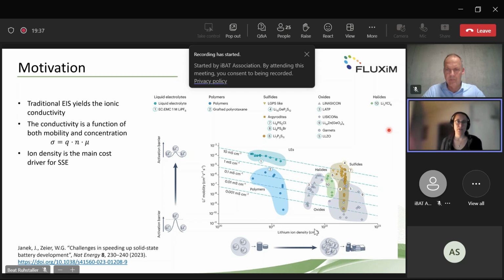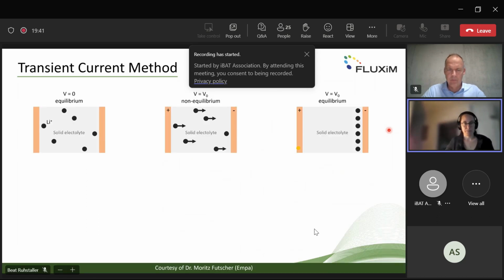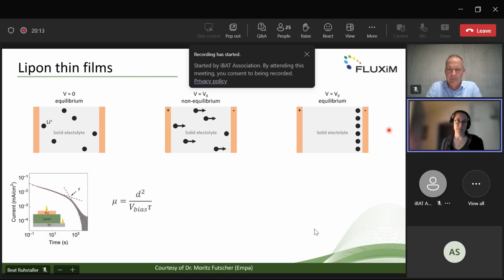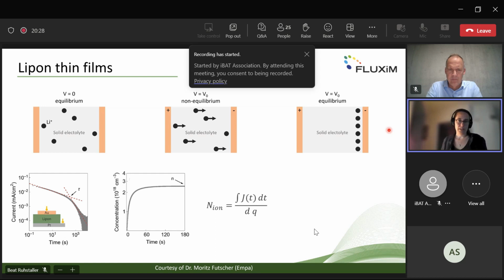in the production. So to introduce this method, it's actually pretty simple. Here is a sketch from Moritz Futscher from EMPA. You have basically a solid electrolyte sandwiched between 2 electrodes. You apply a certain DC potential until you reach a steady state, which is shown here. And basically you monitor during this time the current through these 2 electrodes. And if you check the results, here shown for a Lipon film, you basically get from a log-log plot of the current and the transit time the mobility of the ionic charge carriers. And from the integral, you get the ion density.